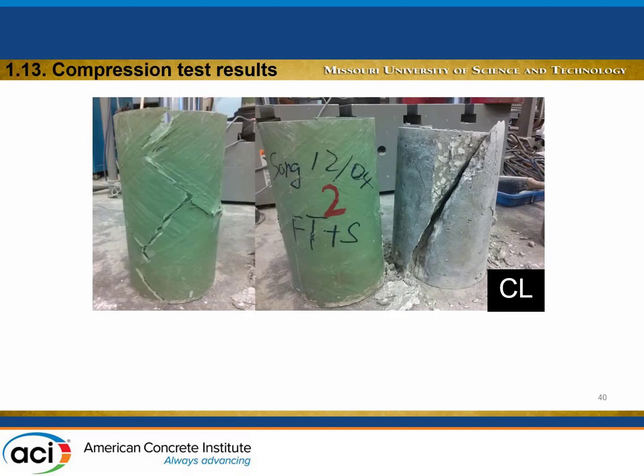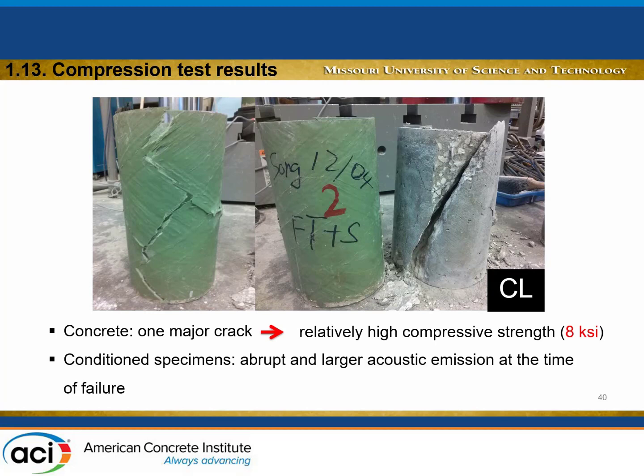Okay, here is the damage. What was really interesting is that after the exposure, typically you see a more brittle FRP. You can see this brittleness even in the sound. The specimen exposed to a longer duration at a higher temperature made a very high sound when it was crushed on the lamp. And for the concrete, because this is relatively high strength concrete, you don't really see too much damage. It's typically a single big crack, and then it continues like this.